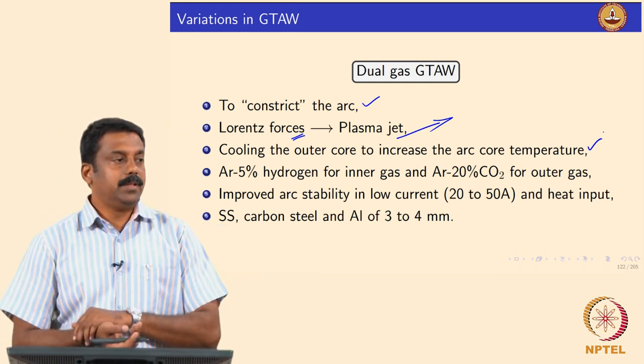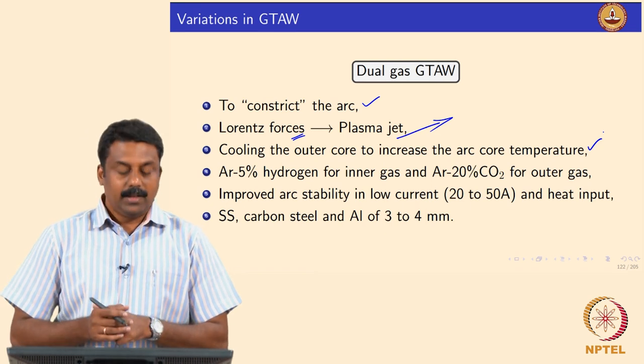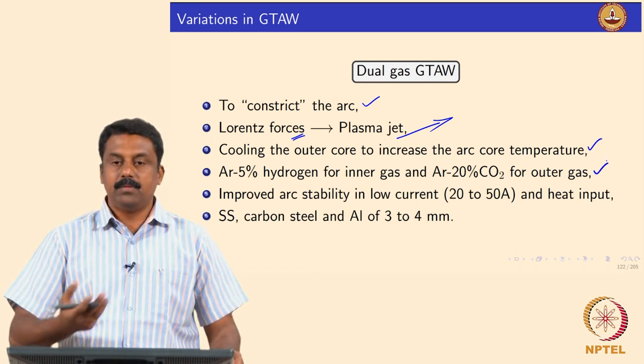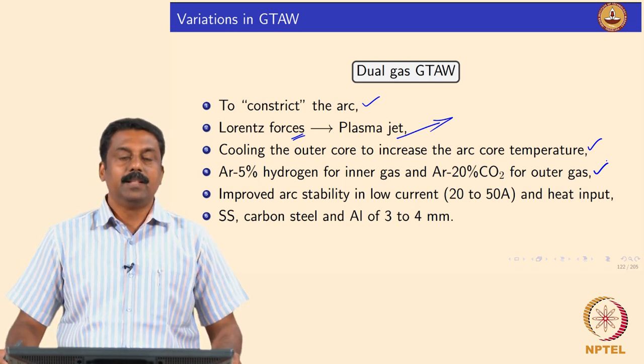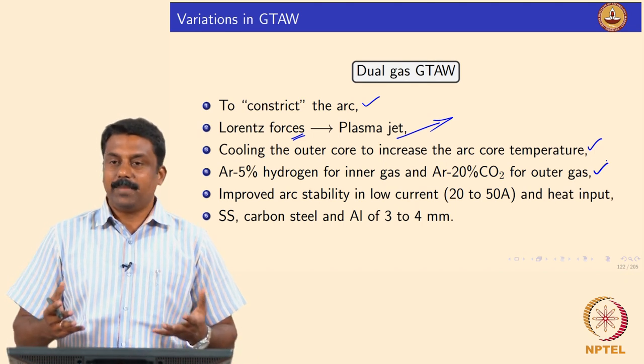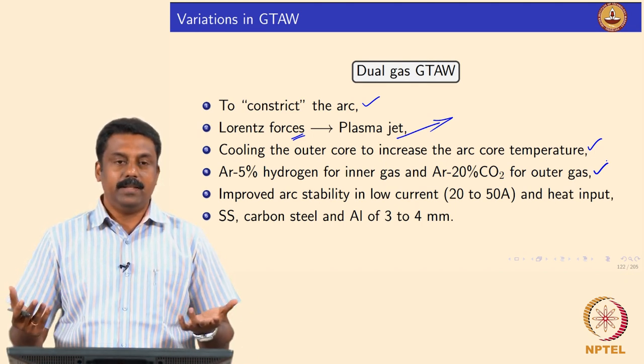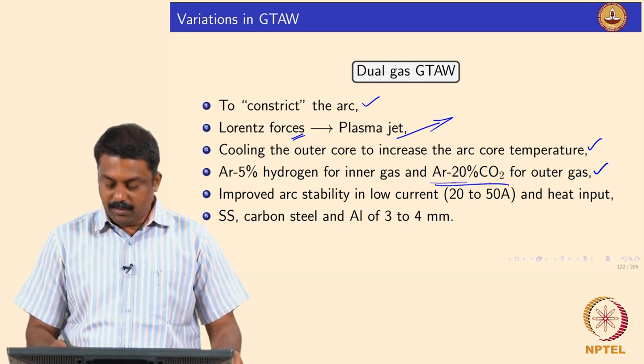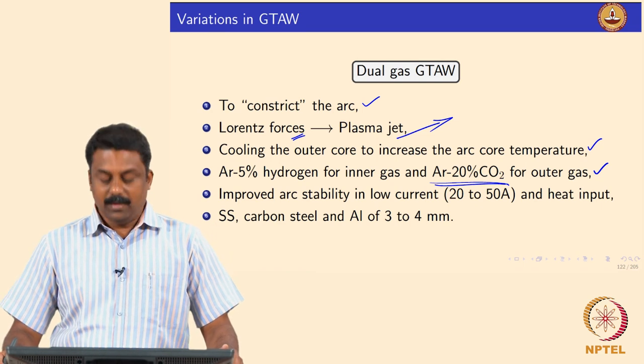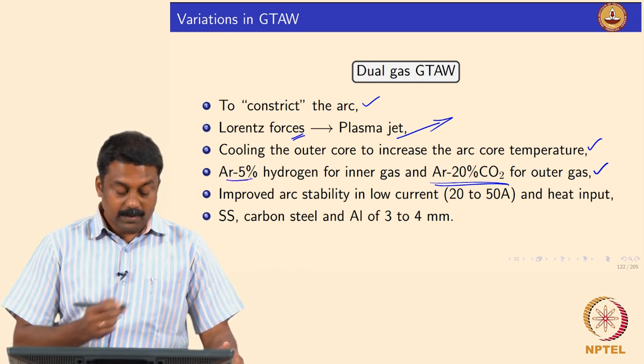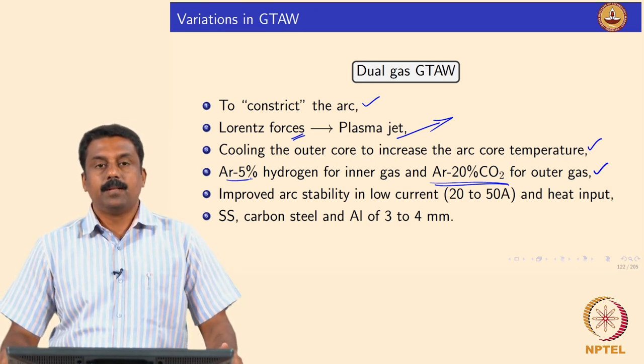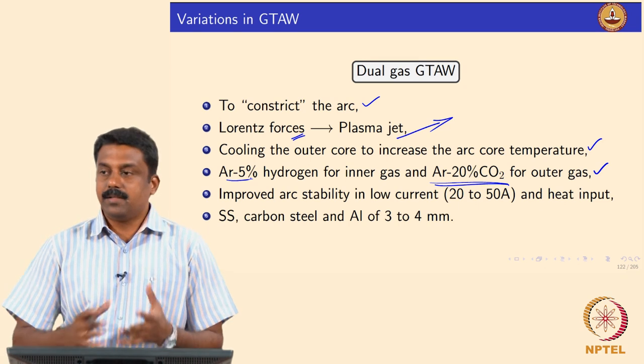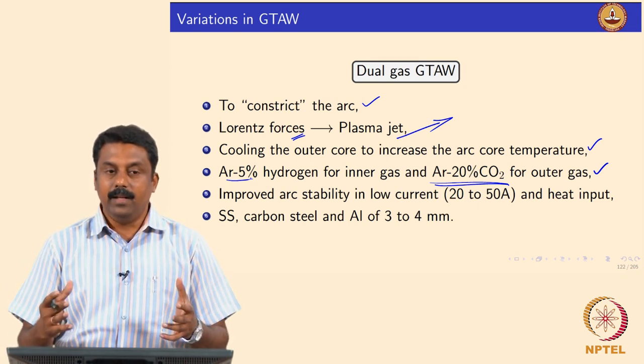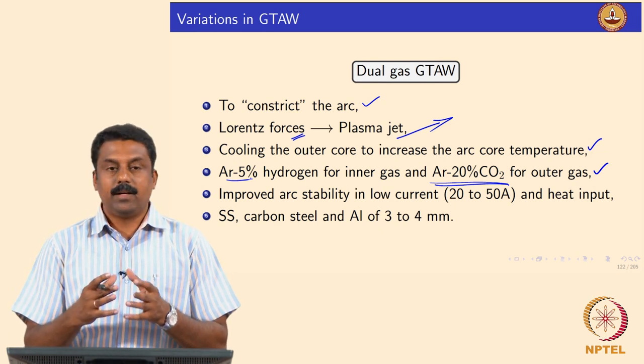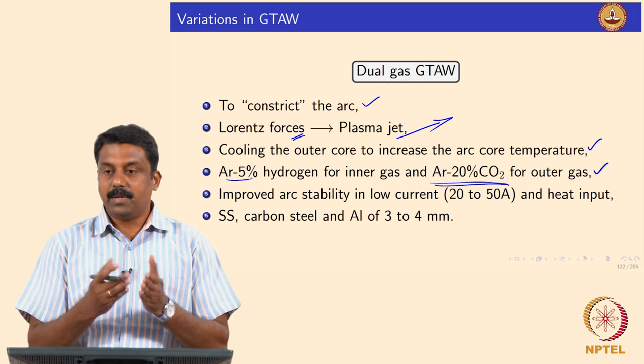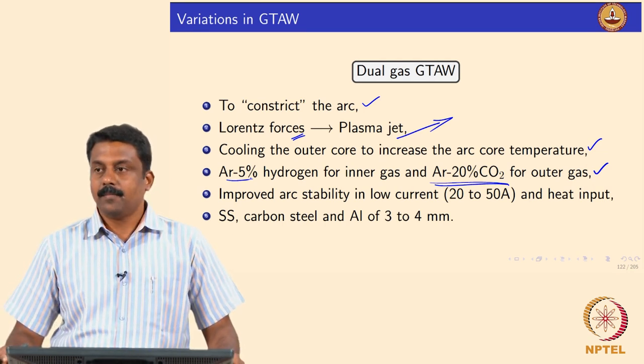Generally argon is used as the plasma gas. We can also use a somewhat cooler gas, argon with 20% CO2, because we need to reduce the temperature, so that when it ionizes, it does not release as much heat. The commonly used outer gas is argon with 20% CO2, and as the inner gas we use argon with 5% hydrogen, or pure argon. So it is also used to create more convection, but we are not allowing it to convect freely. We are constricting it with a colder gas outside, so that the plasma jet can be formed and then transferred to the workpiece. It's clear.